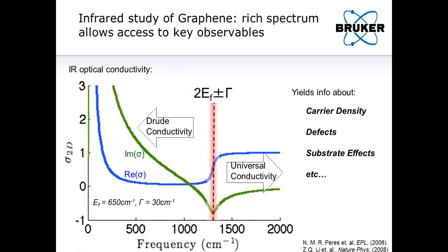With a single infrared spectrum, you can get information about all of these properties, such as the carrier density, which you can extract from this E_Fermi value. You can get information about defects and substrate effects from gamma. And gamma is going to manifest itself as basically the width of this transition that I'm showing here. And by taking these spectra, you can really perform some accurate characterization of graphene samples, which is non-destructive and relatively easy to do.